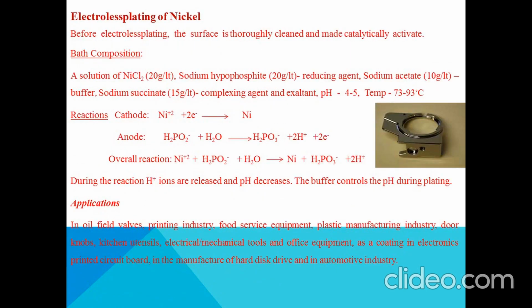How is electroless plating of nickel carried out? During electroless plating of nickel, the surface is thoroughly cleaned and made catalytically active. The catalytically active substrate is then dipped in the plating bath. The plating bath contains a solution of nickel chloride, that is 20 gram per liter. This nickel chloride provides nickel ions for the plating. Then it contains sodium hypophosphite 20 gram per liter, which is a reducing agent. Then it contains sodium acetate 10 gram per liter, which is the buffer added to maintain constant pH. Then the plating bath also contains sodium succinate 15 gram per liter, which is a complexing agent and exaltant.